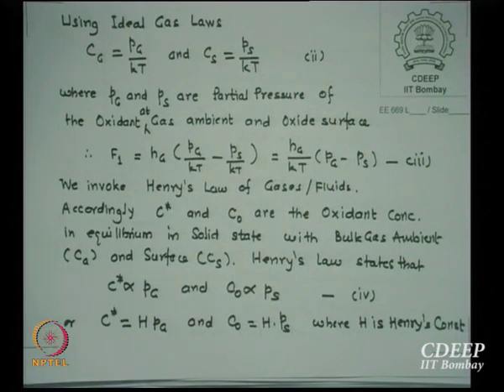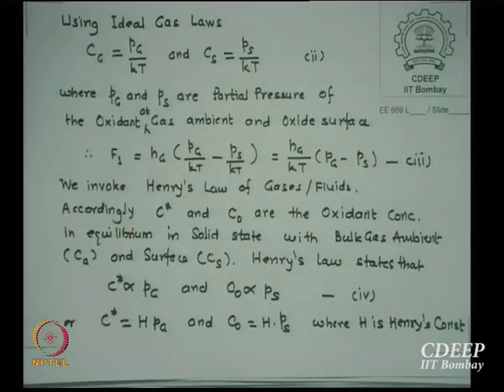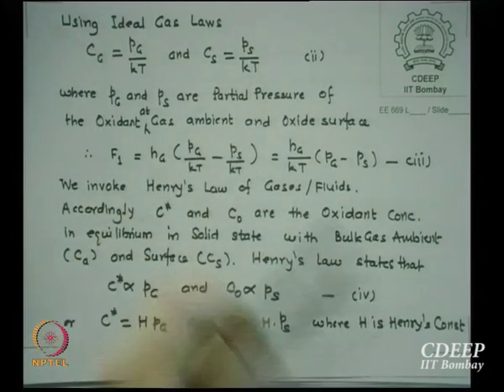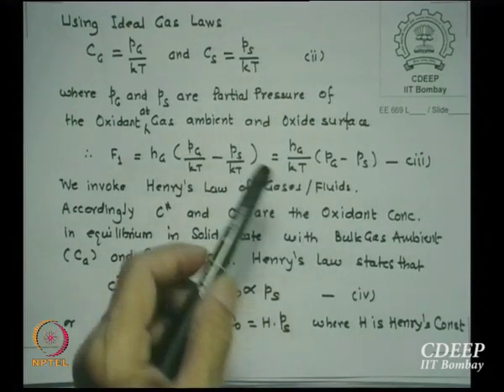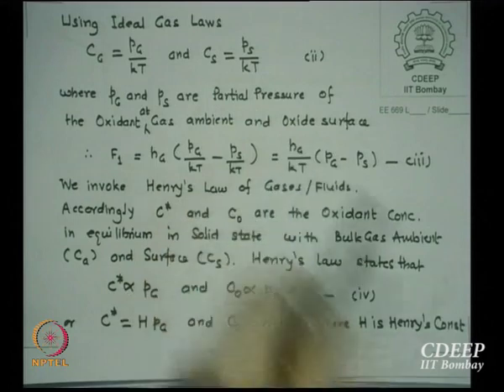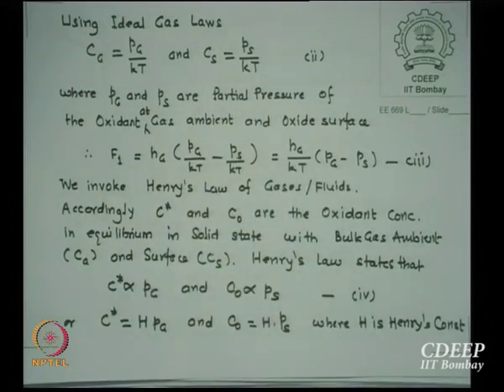So if I substitute Cg and Cs in the last equation by Pg and Ps terms, then I get F1 is equal to hg times Pg by kT minus Ps by kT, or equal to hg by kT into Pg minus Ps. Please remember, if I fix temperature and if I fix the gas flows, total gas flows, hg is a constant which is the mass transfer coefficient proportional to the total pressures. We will see this in the case of CVD.